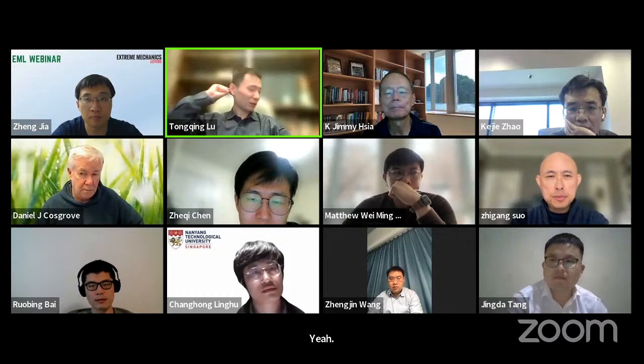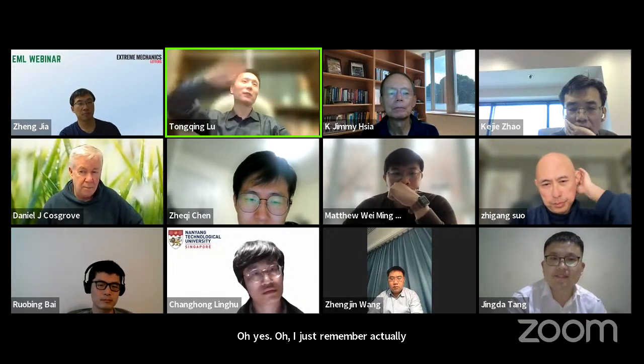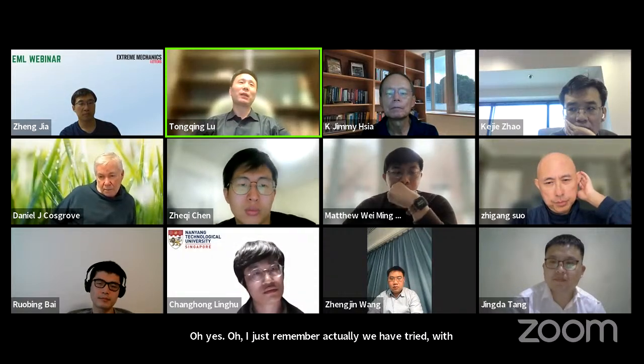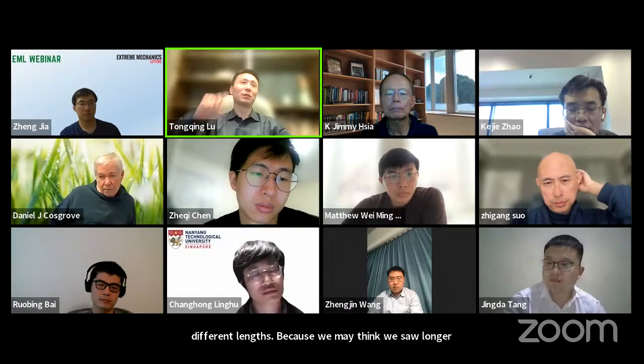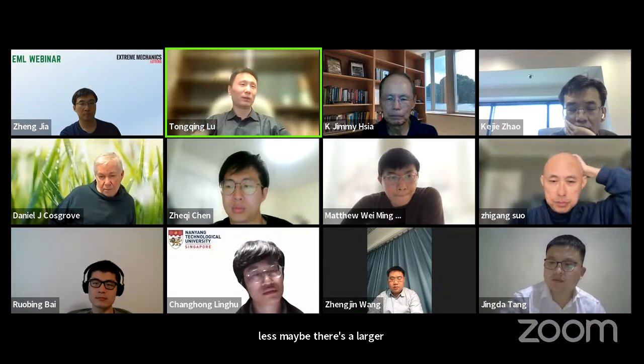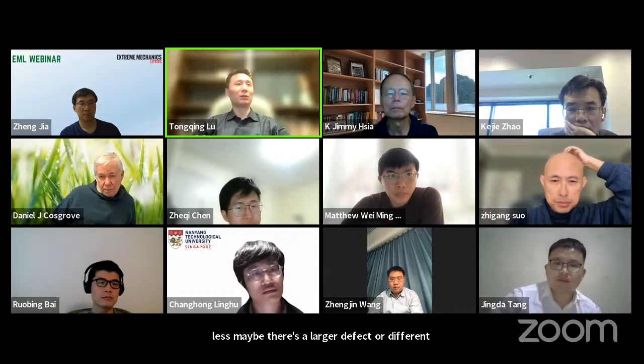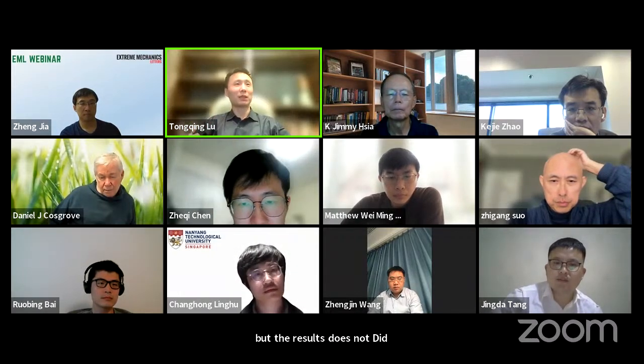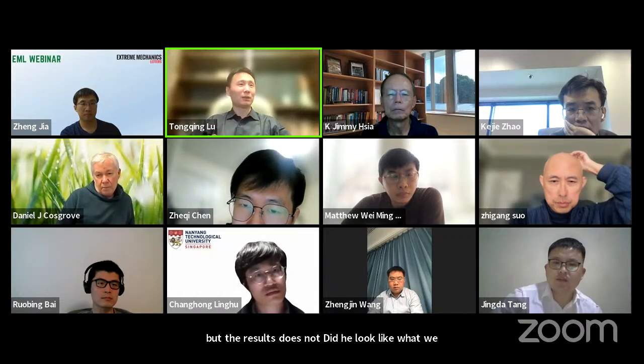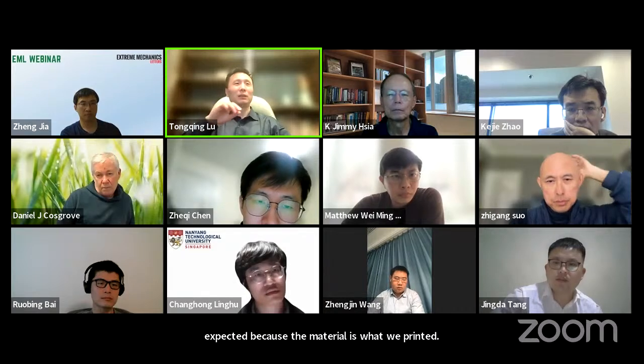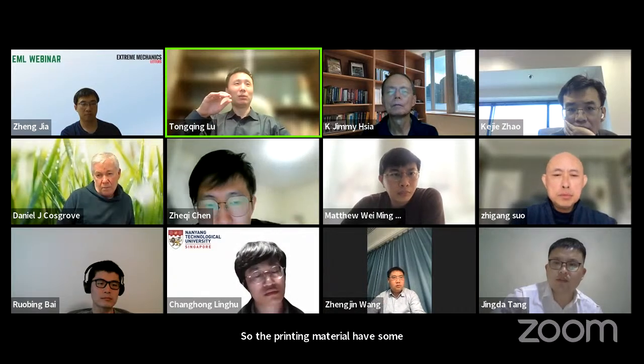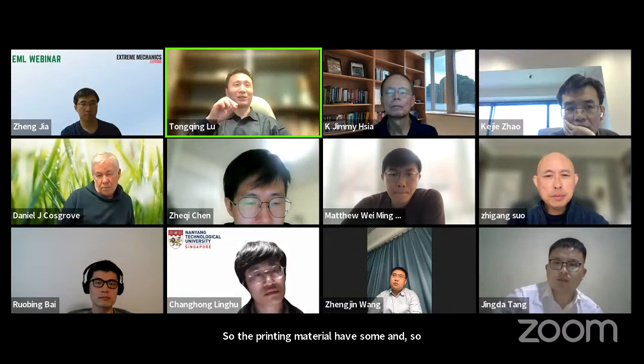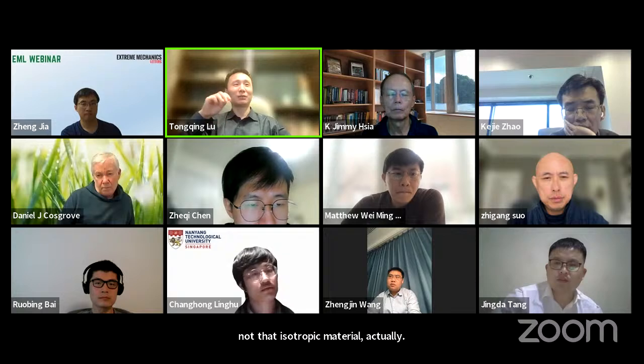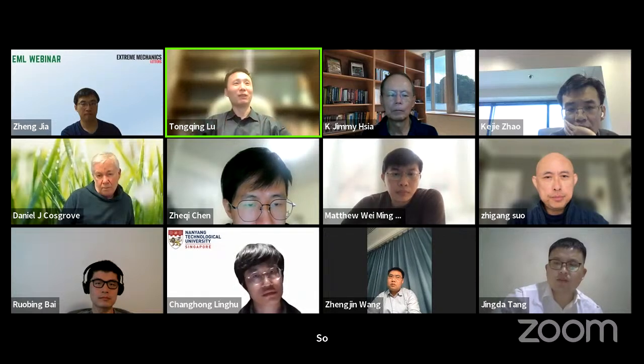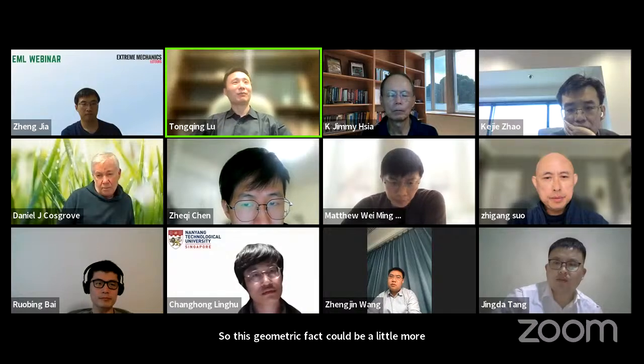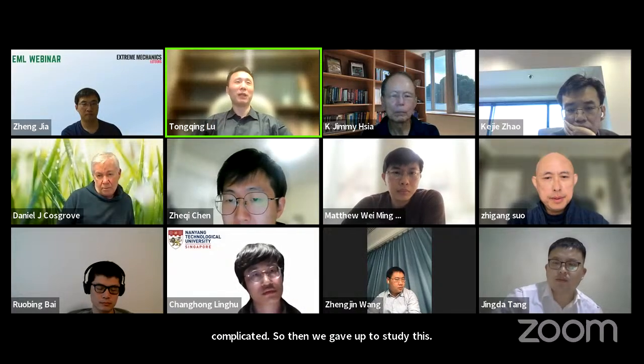Oh, yes. I just remembered, actually, we have tried with different lengths, because we thought with a longer length, maybe there's a larger defect or different weights. But the results do not look like what we expected, because the material is what we printed, and the printing material has some anisotropy. So it's not an isotropic material actually. So this geometric effect could be a little more complicated. So then we gave up studying this effect. It all depends on how you prepare samples actually.